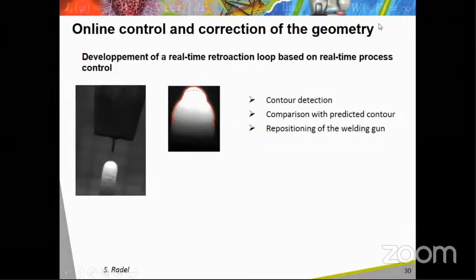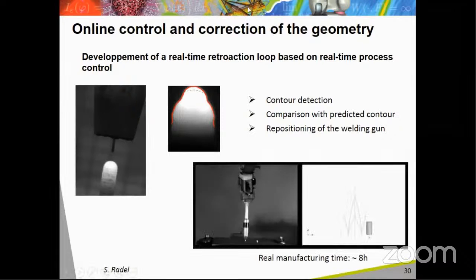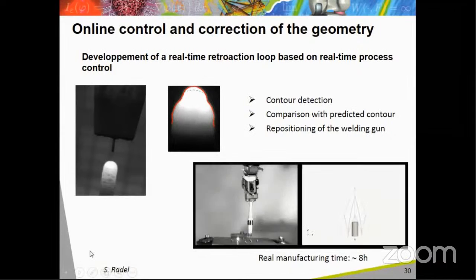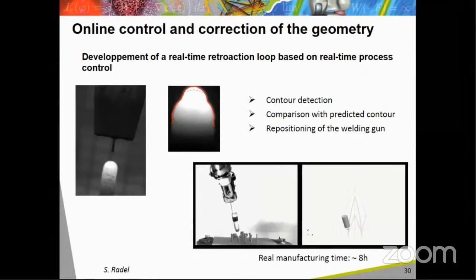Based on this monitoring system, a retroaction loop has been developed to adjust the bead strategy in real time. For that, the real bead contour obtained is first compared to a predicted contour, and a real-time retroaction loop has been computed for repositioning the welding gun at each new deposit. In this video, we can see the real construction and the predicted one for a complex filariform structure. Note that the build speed is greatly accelerated in this video, the real manufacturing time of this component being about 8 hours.